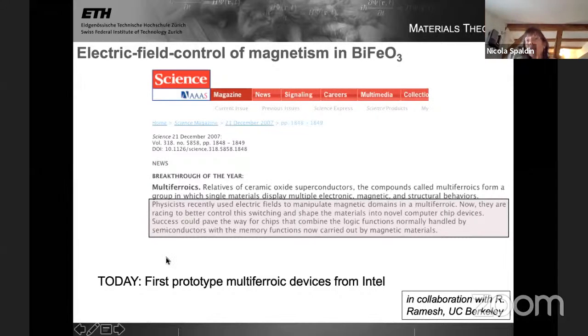Yeah, so in bismuth ferrite, of course, the oxygen-ion interaction is the strongest magnetic energy scale, and it's almost 180-degree super exchange. So it's a really, really robust antiferromagnet because the super exchange is the dominant interaction. I'm not sure if that answers the question or not.